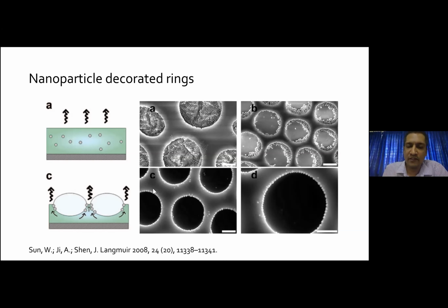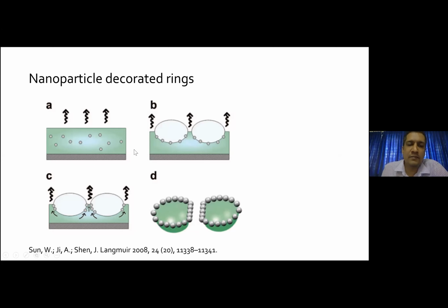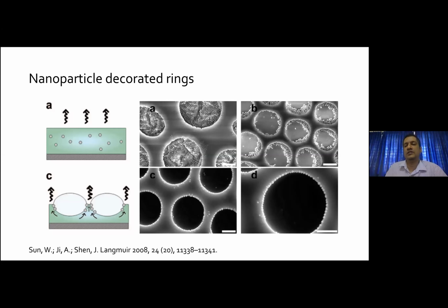If you carefully see the mechanism proposed by them, during the process of evaporation, the particles migrate from the interior towards the ring, which means that the particles have some kind of surface functional groups that are attracted towards the hydrophilic environment. It is a porous silica particle with some fluorophore inside it, to have an optical or fluorescence image taken at a later stage.